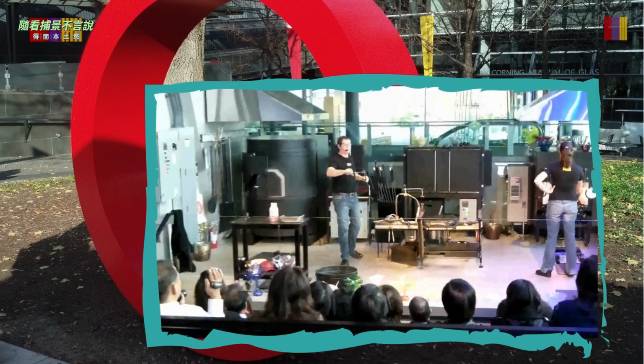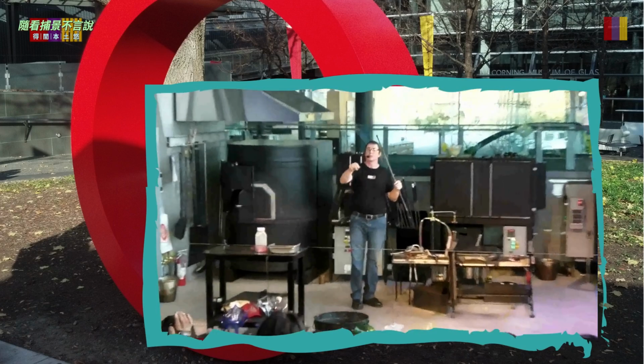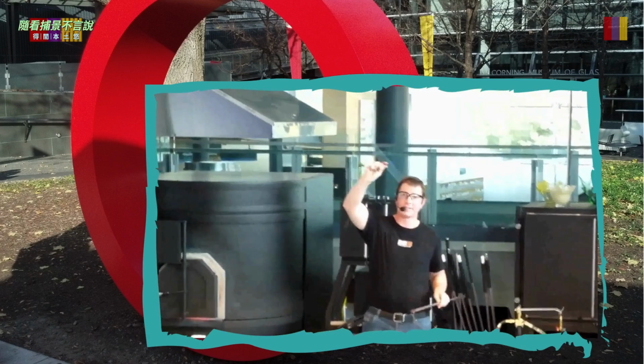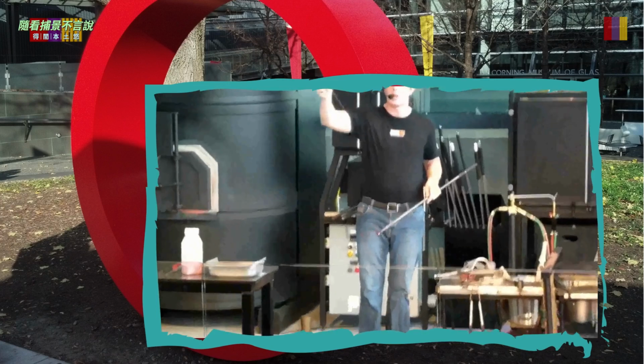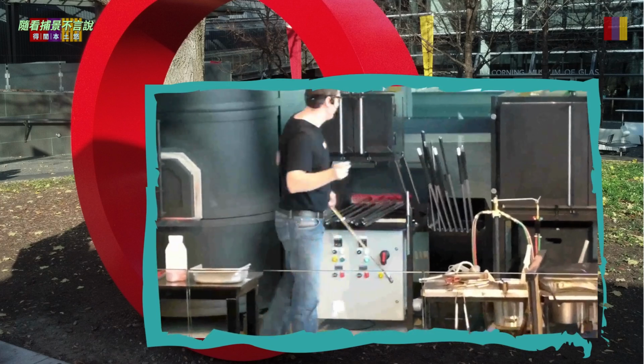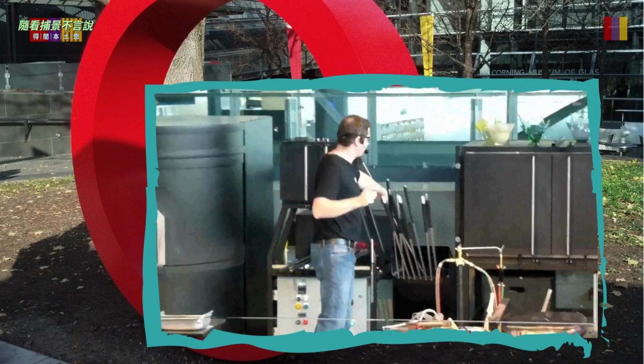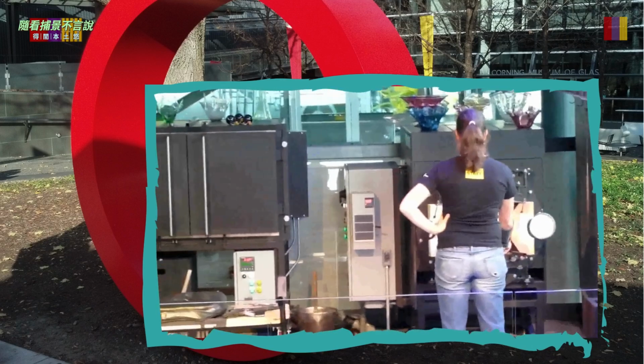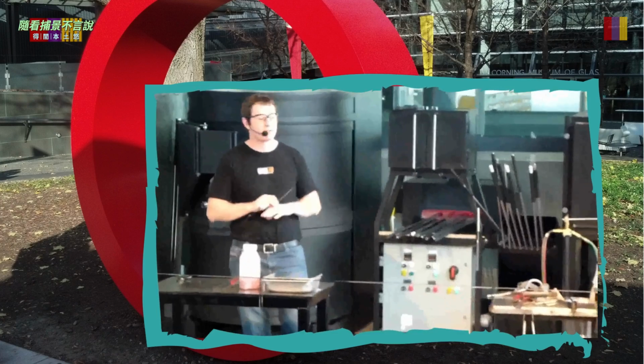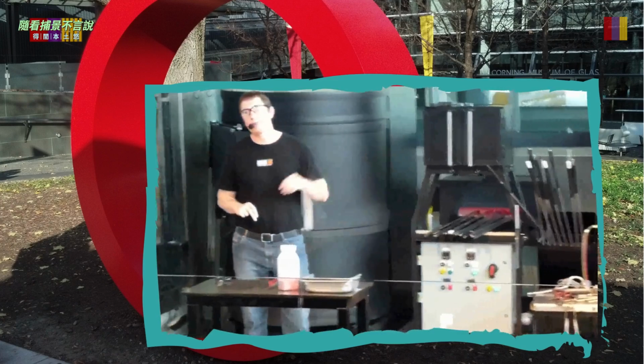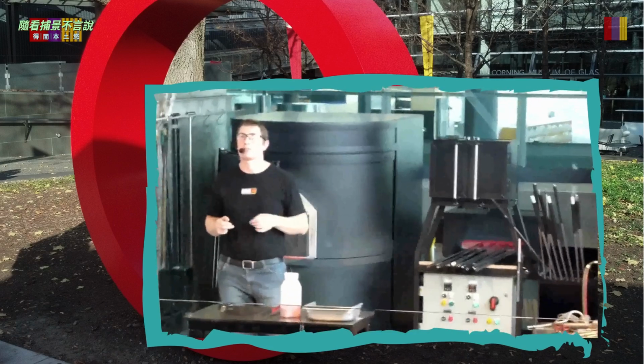You know, when glass is thin, it's actually very flexible. I can almost tie this into a knot. And also, remember, just less than 5 seconds ago, this was 2,000 degrees. Already, it's cooled down to room temperature, where I can hold it in my hands. And the rate at which this cools is our biggest challenge. You know, if Annette's bowl drops below 1,000 degrees Fahrenheit, it will crack and shatter right on the end of her pipe. So throughout this entire demonstration, it's very important that Annette keeps this bowl above 1,000 degrees Fahrenheit.